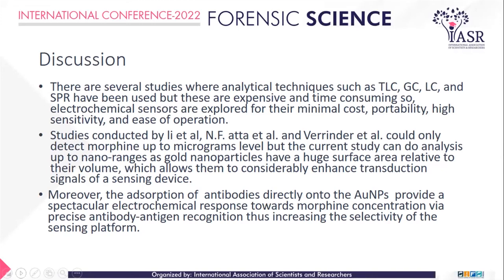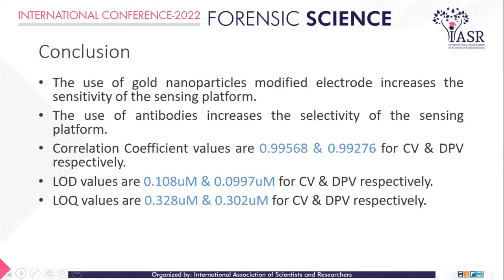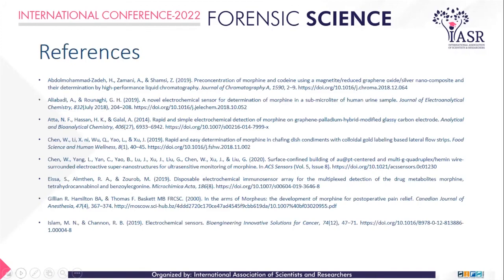In conclusion, the use of gold nanoparticles increases the sensitivity of the sensing platform, and the use of antibodies increases the selectivity of the sensing platform. Correlation coefficient values for CV and DPV mode came out to be 0.99568 and 0.99276 respectively. LOD values for CV and DPV are 0.108 micromole and 0.0997 micromole respectively, and LOQ values are 0.328 micromole and 0.302 micromole for CV and DPV respectively. These are the references, and thank you.